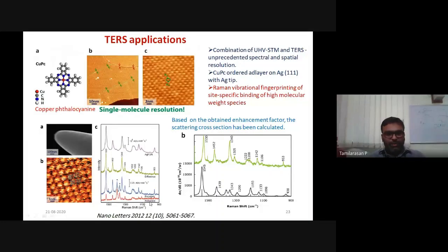And they also did a study with the engaging and retracting related one. So while you are engaging, you will get more peaks. While you are retracting, you will get fewer peaks. If you take the difference between these two, you will get the exact spectrum corresponding to the copper phthalocyanine. So using this copper phthalocyanine spectrum, they have back calculated the scattering cross section. Instead of being 10 power minus 30, the scattering cross section has been increased 4 orders to 10 power minus 26 here. So using this method, you can actually go for intramolecular orientation, intramolecular site-specific findings, or intramolecular site-specific electrochemical reactions can be possible.